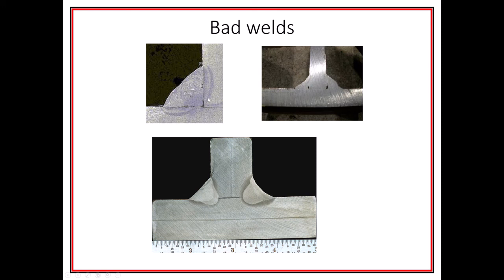The best way to judge a weld, unfortunately, is destructive testing. To actually take the weld and cut it apart, and then etch it, polish it up, and do some penetrating dye into it. And you could see there are these gaps inside, and that it's not penetrating all the way through. So these are bad welds. But unfortunately, obviously, you can't do that with a finished weld.